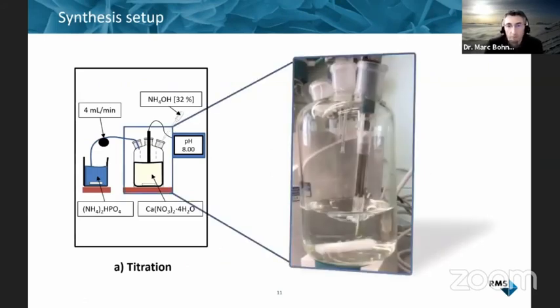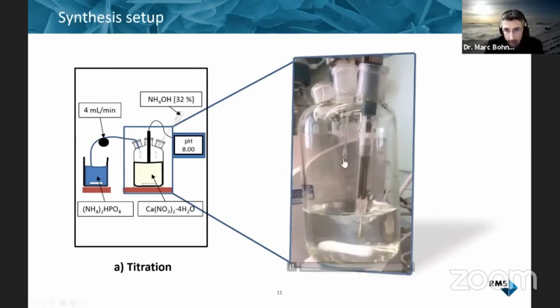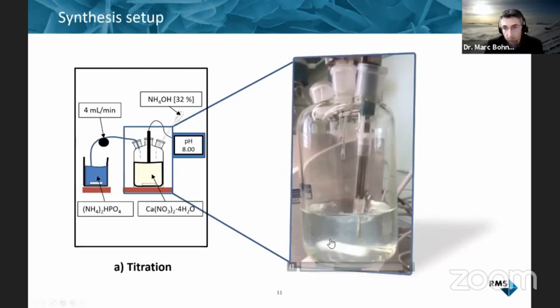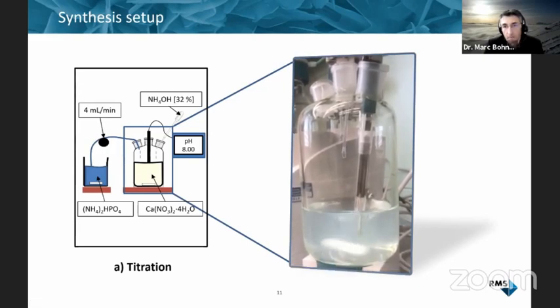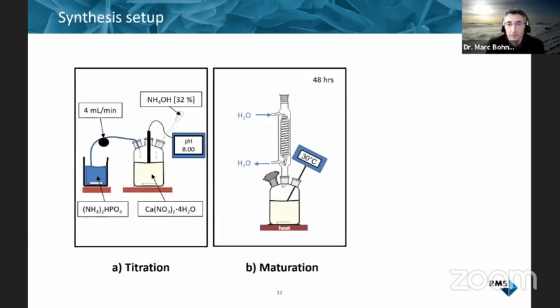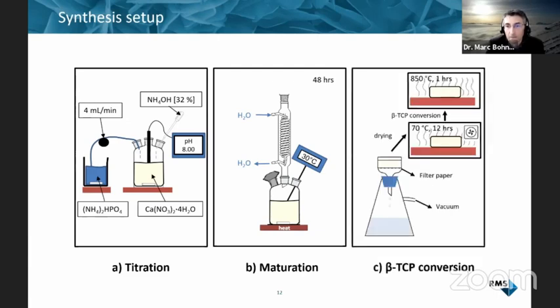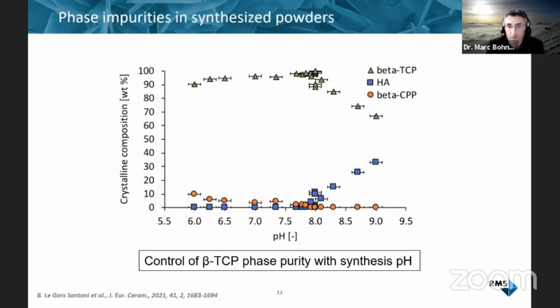I hope you see my video. So basically, we added the ammonium phosphate solution into a calcium nitrate solution. And at the back, we control the pH with ammonia solution. So in that case, we kept a pH of 8. You can see the fluffy or this whitish powder. This is amorphous calcium phosphate. If you leave it for 2 days at 30 degrees, you will form calcium deficient hydroxyapatite that you can then filter, dry, and convert to beta-TCP at 850 degrees.